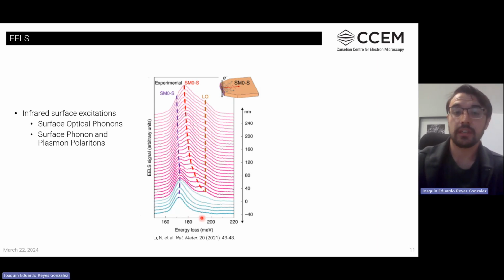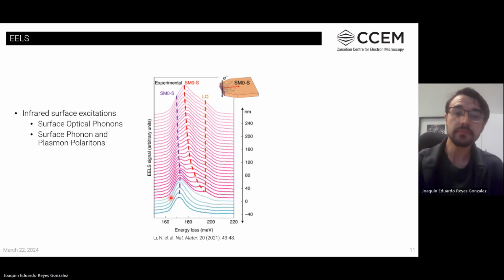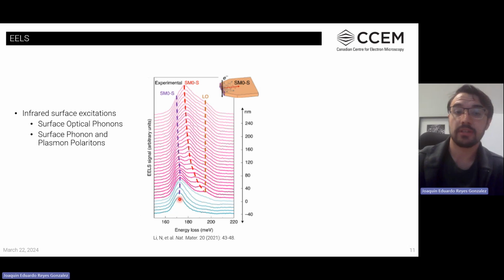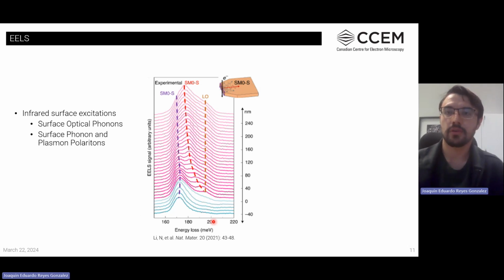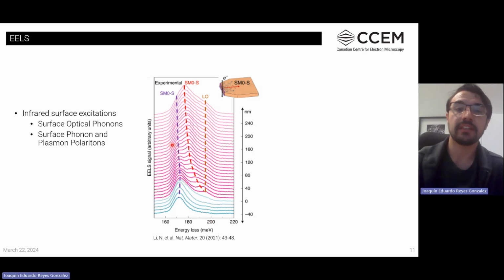As you can see, the experiment reveals small changes in the structure of the optical phonons of the material, and the phonon polaritons forming on the surface and then propagating throughout the whole layer. In this case, it is possible to identify at least 3 excitations confined within a region of 25 milli-electron volts. The high energy resolution achieved on Nion is what allows us to separate this signal and properly follow the behavior they have throughout a structure.